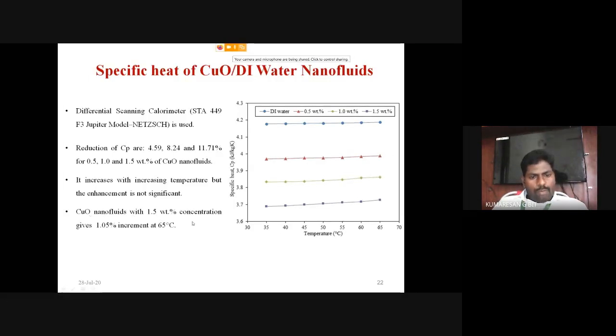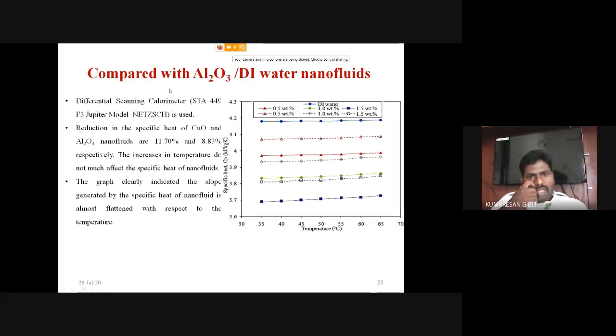Then CuO nanofluids with 1.5 wt.% concentration give only 1.05 increment at 65 degrees Celsius temperature. This study is conducted only up to 65 degrees Celsius, because I conducted the experiment only up to 65 degrees Celsius. Then compared with Al2O3 DI water nanofluid, you see here CuO, that means copper oxide nanofluid, and Al2O3 nanofluid, both the specific heat values with respect to the temperature are almost similar, because the addition of nanoparticles in the base fluid does not have any significant impact on its specific heat value.